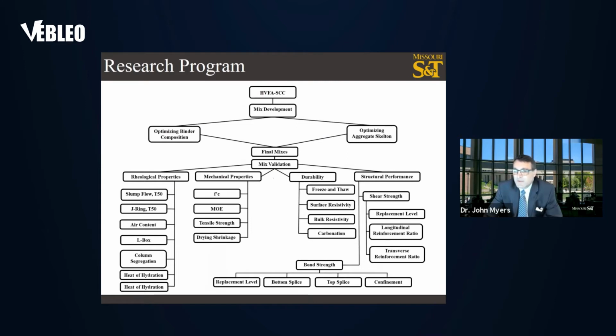This flow chart summarizes the research program of developing and investigating the performance of high volume fly ash SCC. The first step was developing the mix design. The development went through 2 phases: optimizing the binder composition, followed by optimizing the aggregate skeleton, and then coming up with a final mix. Once the mix has been developed, it needed to be validated in terms of its rheological properties, the mechanical properties, the durability, and then finally the structural performance, including the bond strength. Under each of these, you can see the key tests or evaluation criteria that were used to assess the performance